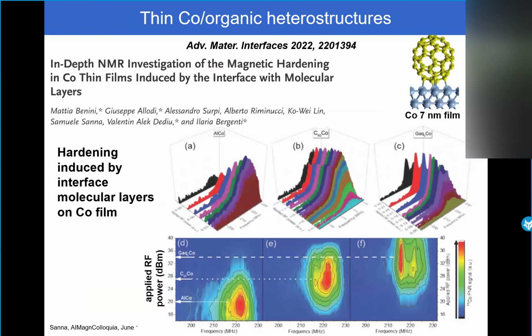Just to tell you that we used very successfully this technique to study these very nice cobalt thin films covered by different capping layers, to demonstrate that hardening of the magnetic properties of the system is induced by interface molecular interactions. In particular, you can follow in this plot.